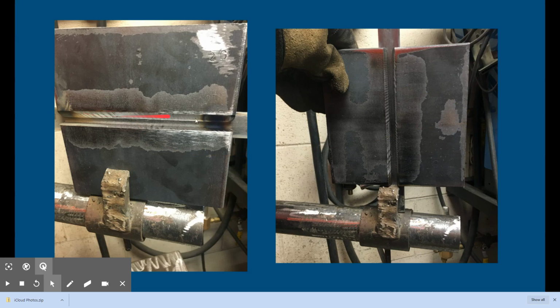So again, 2G, there's my 2G stamp. This is how it's going to be set up. You can see the bottom piece is not beveled here. The top piece is beveled at a 45. You can see I've ripped the mill scale off around the front. You don't have to take the mill scale off the entire plate, just around the front of the weld, and then around the back, same thing, and on the back side, just where the weld's going to go.